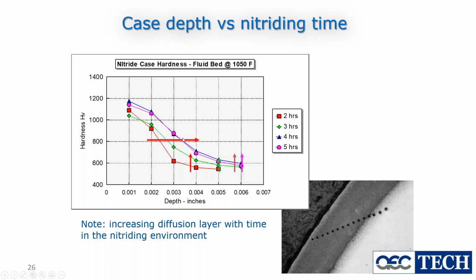4 and 5. At this point, you don't see a lot of difference between 4 and 5, but when we look down at the critical area, which is where the gray goes into the dark gray here, you start to see that at about 3.75 thou at 2 hours is our total case depth. At 3 hours, that's gone out to 5 thou. At 4 hours, it's gone out to about 5 3/4, and at 5 hours, it's gone out to 6 thou. So we're pushing the nitrogen deeper and deeper in.